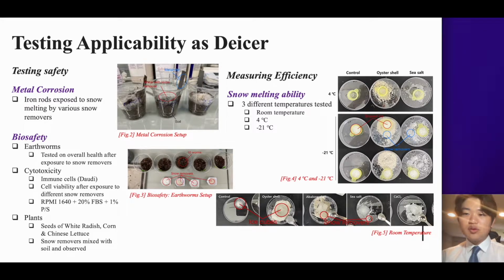Biosafety tests were performed in 3 parts. Tests were performed on earthworms, cells, and plants. In tests with earthworms, 10 earthworms were used for each test condition, and the overall health state of the earthworms was tested after exposure to the different de-icers. Cell safety was tested using immune cell line Daudi, and the cell viability was measured after exposure of the cells to various de-icers. RPMI 1640 was used as a medium for cell culture.